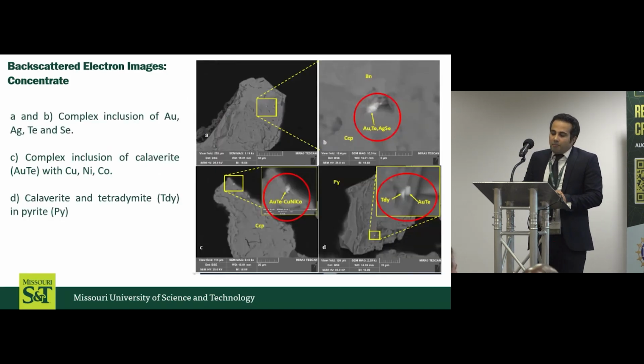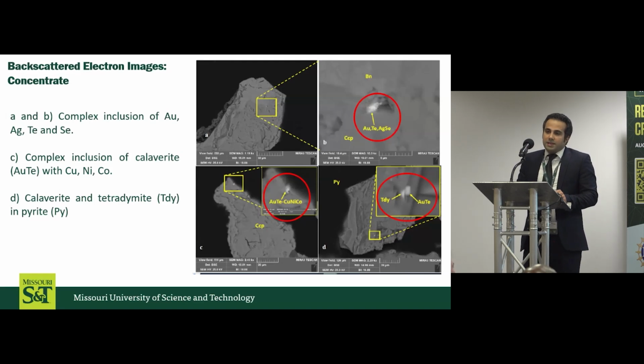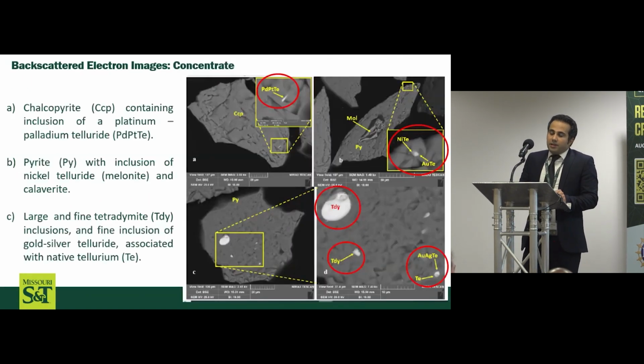In this slide, you can see the complex inclusion of gold, silver, tellurium, and selenium in chalcopyrite and bornite, a complex inclusion of calaverite with copper, nickel, and cobalt. And you can see the calaverite and tetradymite minerals in pyrite. We found chalcopyrite containing inclusion of a palladium telluride, pyrite with inclusion of nickel telluride, melonite, and calaverite, and a very interesting backscattered image: large and fine tetradymite inclusions and fine inclusion of gold-silver telluride associated with native tellurium.